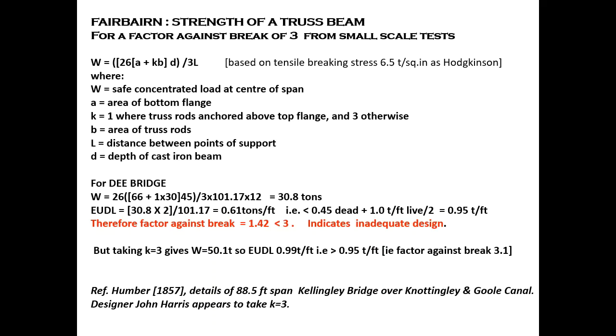And in this case at Dee Bridge we're anchored above, of course. If you go through the calculation, you'll find that the bridge was inadequate according to Fairbairn. The factor against break is 1.42, whereas it should be at least 3 according to Fairbairn. So Fairbairn wasn't very happy, and in the 1849 inquiry into bridges, this all appears, and Fairbairn was pretty unhappy about this method of construction.